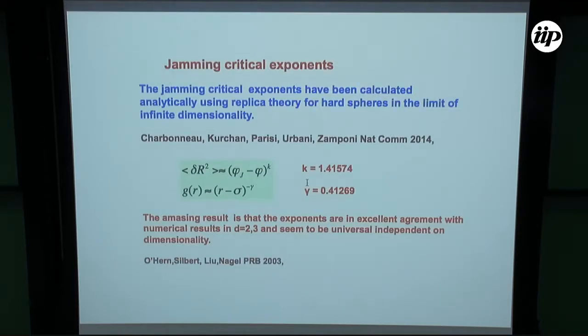What is also interesting is that these people, always including our chairman, calculated the jamming critical exponents analytically using a replica theory for hard spheres in the limit of infinite dimensionality. And the amazing result, I was very impressed, I must say, by this work, is that these exponents, which are calculated in mean field, or if you like, in infinite dimensionality, are in excellent agreement with the numerical results in d equals 2, 3, and even more dimensions, and so seem to be universal exponents, independent of dimensionality.